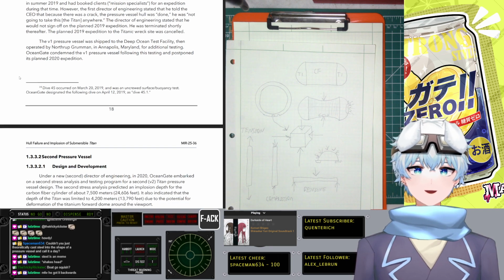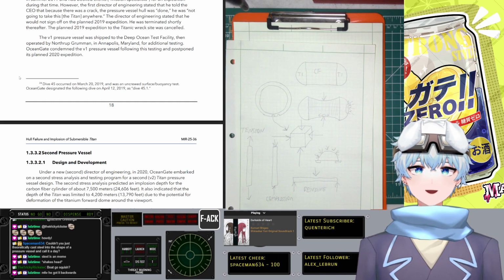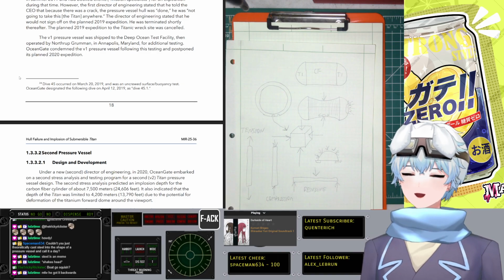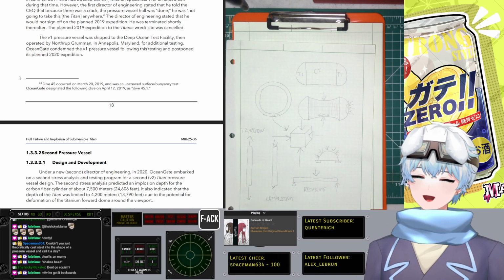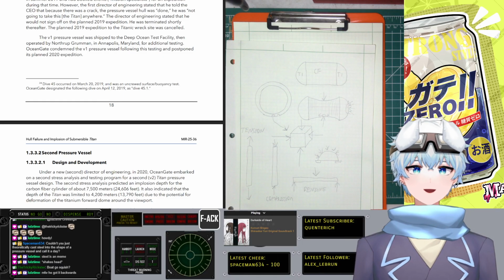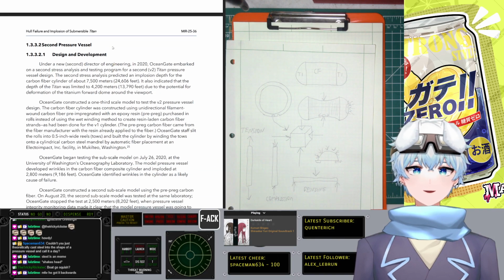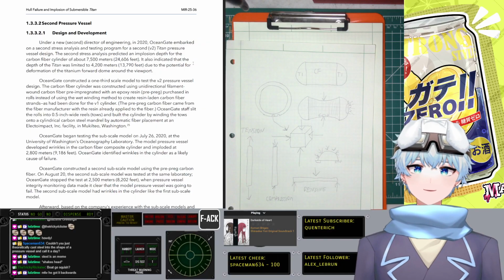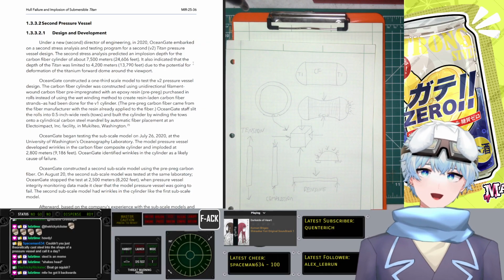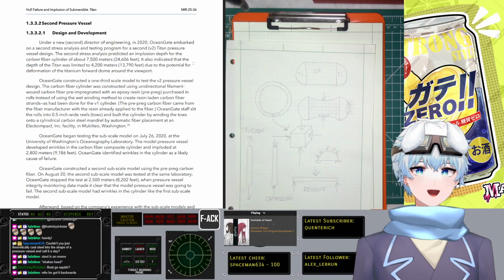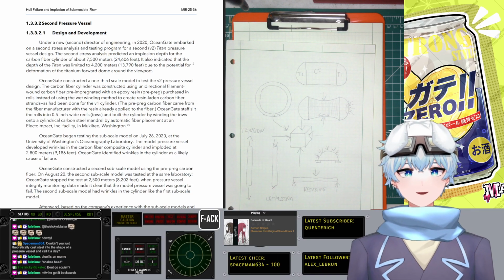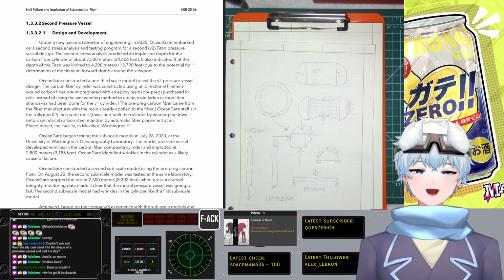The V1 pressure vessel was shipped to the Deep Ocean Test Facility, then operated by Northrop Grumman in Annapolis, Maryland. Shout out to our resident Northrop Grumman employee here. And following this testing, it postponed its planned expedition. Second pressure vessel test. This is where things get really spicy. Under a new director of engineering, they embarked on a second stress analysis and testing program for a V2 Titan pressure vessel. It predicted an implosion depth of about 7,500 meters, but also indicated that the depth of the Titan was limited to 4,200 meters due to the potential for deformation of the titanium forward dome around the viewport.